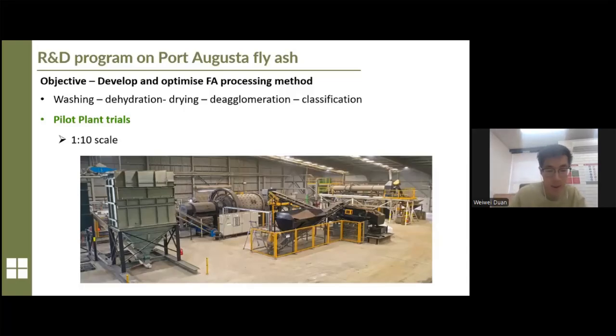We are trying to understand the fly ash characteristics, and followed by that, we have another stage, which is to develop and optimize the fly ash processing methods. The processing methods we currently include are washing, dehydration, drying, de-agglomeration, and classification. To start with, we built a pilot plant at 1 to 10 scale at Dry Creek to refine the technologies for chloride removal and also washing and milling of the coarse fly ash.